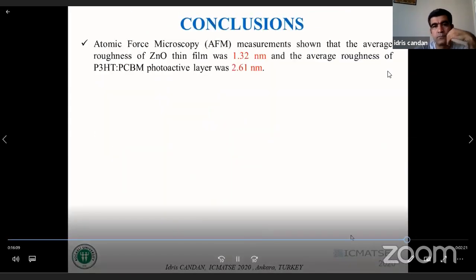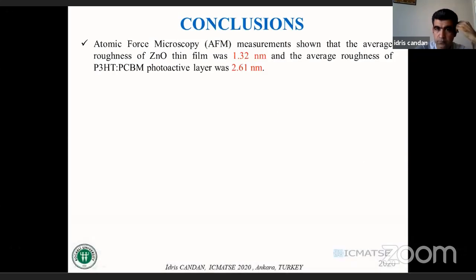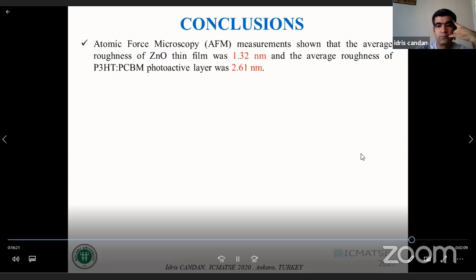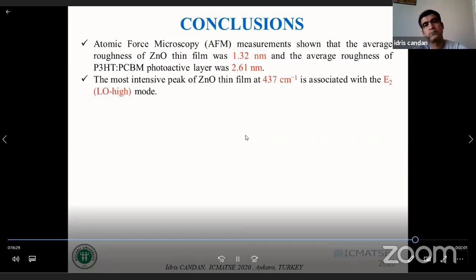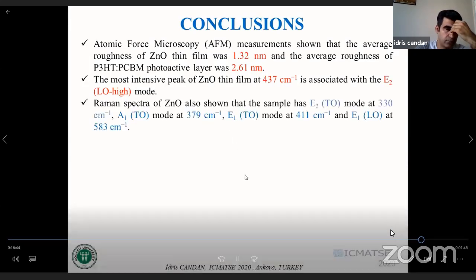As a conclusion, atomic force microscopy measurements showed that the average roughness of zinc oxide thin film was 1.32 nanometer, and average roughness of the P3HT:PCBM photoactive layer was 2.61 nanometer. The most intense peak of the zinc oxide thin film at 437 centimeter to the power of -1 is associated with E2 high mode, and the Raman spectra of zinc oxide also showed